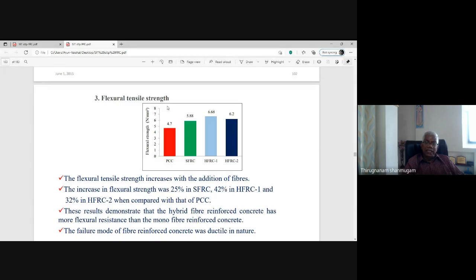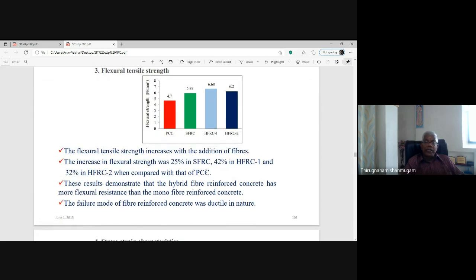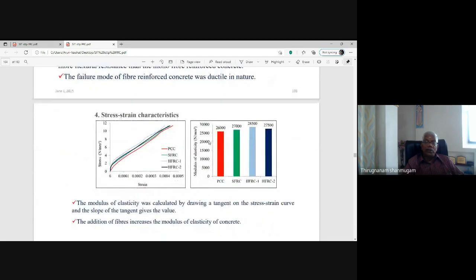Similarly for flexural tensile strength, the prism specimens are subjected to 2-point loading. We are estimating the flexural strength as PL by BD square, 4.7 Newton per mm square for PCC or control concrete, and 5.9 Newton per mm square for fiber reinforced concrete, and 6.7 Newton per mm square for hybrid fiber reinforced concrete. 25% or 30% increase. As per the literature also, 30% increase in flexural strength is obtained by using 0.75% volume fraction of fibers. Similarly here also.